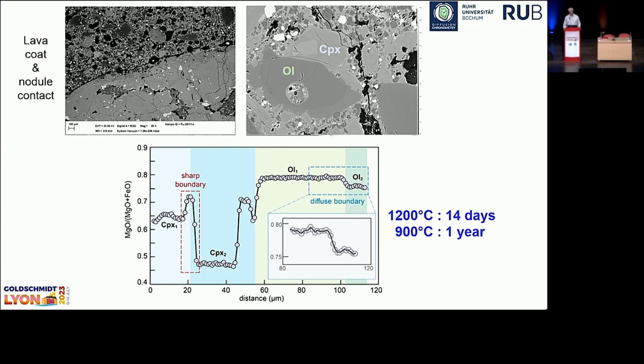And what you see is that the boundary between the pyroxenes is extremely sharp. So even though they're hot, these are two different compositions sitting in a lava at hot temperature. They did not have time to diffuse or mix properly. But olivine, where diffusion is a little bit faster, did have the chance to do that. And that you see in a zoomed out inset where you see a profile which you can then model. And the same uncertainty that you have with the depths, you have with the temperature as well. But because this is a liquid, a lot of liquid, it had to be somewhere between 900 and 1200 degrees centigrade. And if you take that, then it turns out to make that olivine diffusion profile, if you take 1200 degrees, you take about 2 weeks, 14 days. If you take the lower end, the 900 degree temperature, it takes about a year.